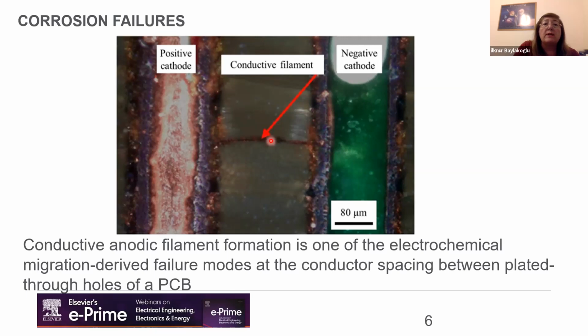This transportation path of metal ions can form at the fiber resin. This is actually the insulation layer, and this fiber resin interface may be affected by the manufacturing quality of the printed circuit board, or maybe the material properties, maybe because of the thermal cycling, and some other factors may contribute to having this conductive filament. And the water molecules and copper ions produced at this anode side, and then they move to the cathode side along the moisturized transport path, forming a copper filament.